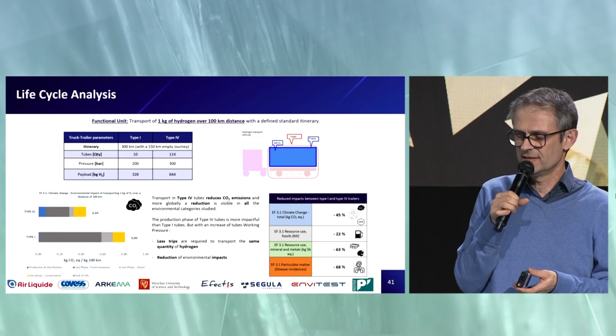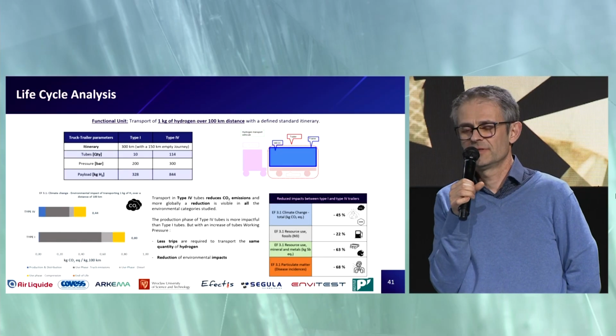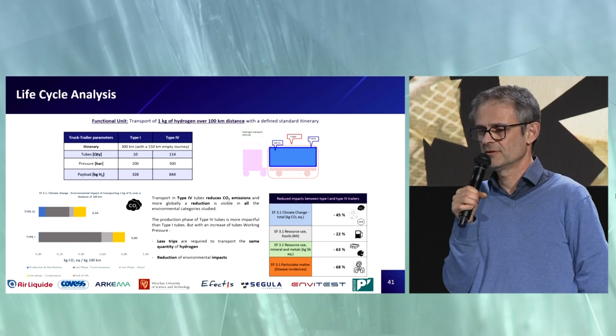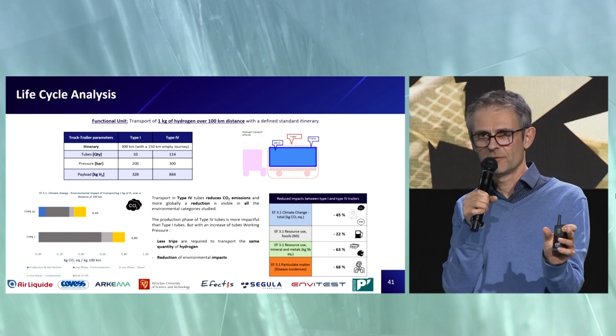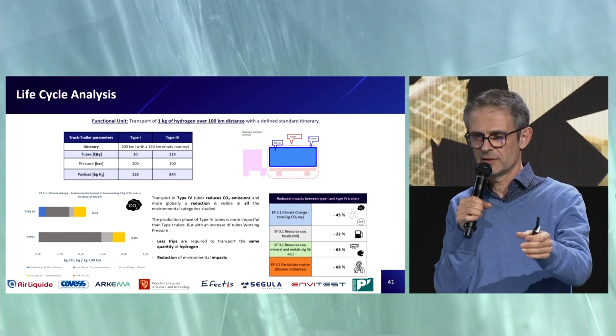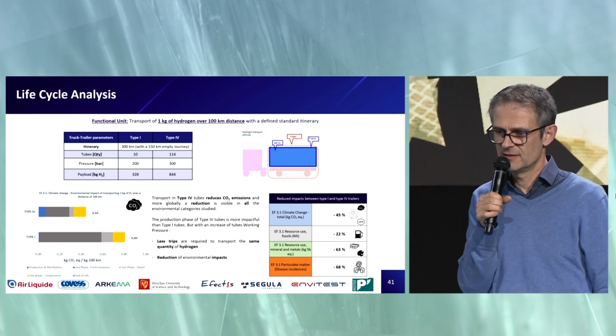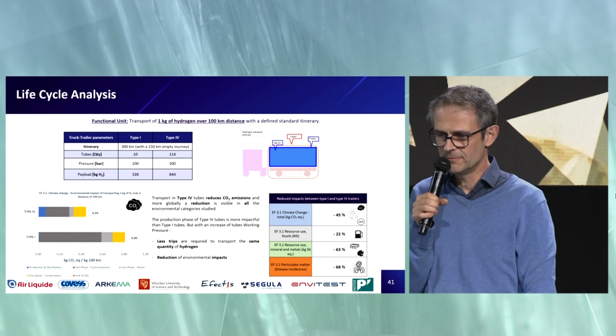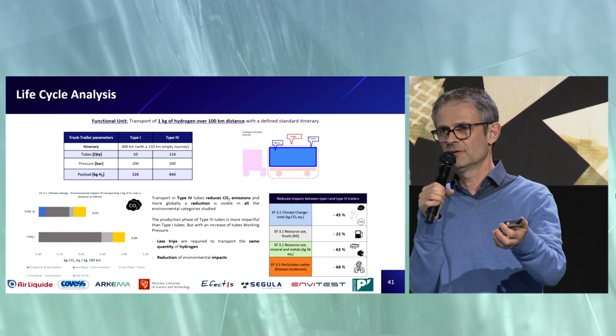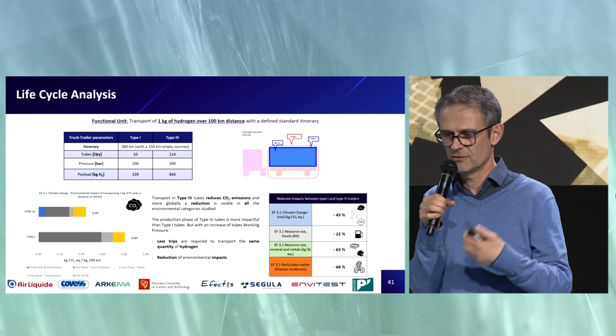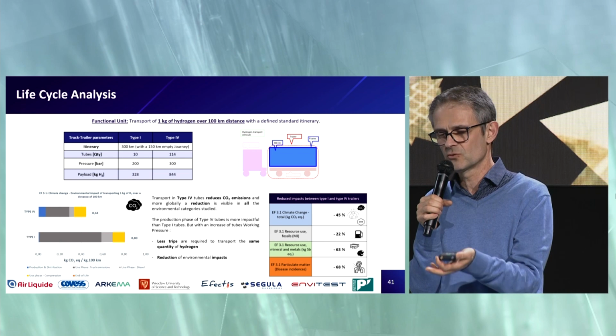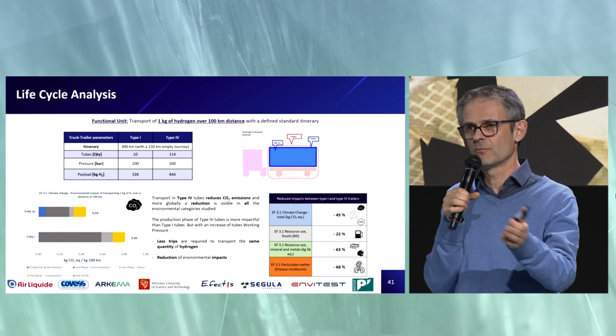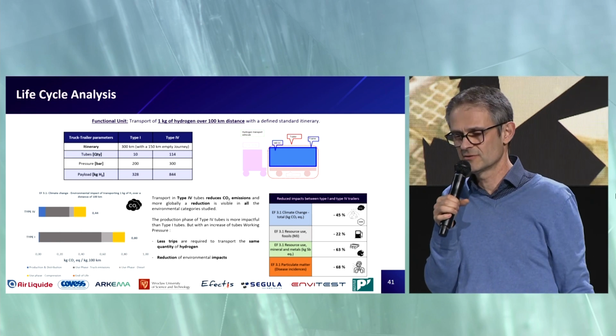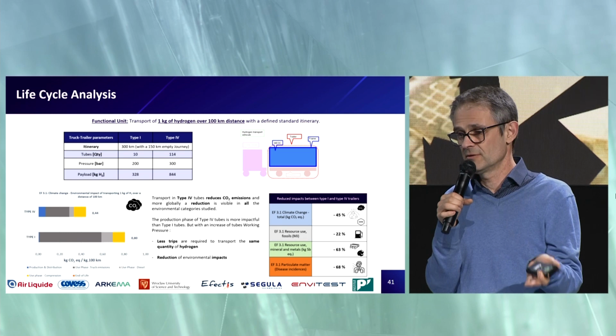Now, about the life cycle analysis. We took the example of 1 kilogram transported over 100 kilometers on a trailer. So far we compared type 1 and type 4 cylinder. And we can see that on many of the environmental aspects, which can be CO2 emission, fuel emission, depletion of mineral resources, we still have quite a good saving for type 4 compared to type 1, and that can be quite easily understood as with the type 4 cylinder, you have to make fewer trips to deliver the same amount of hydrogen compared to type 1.